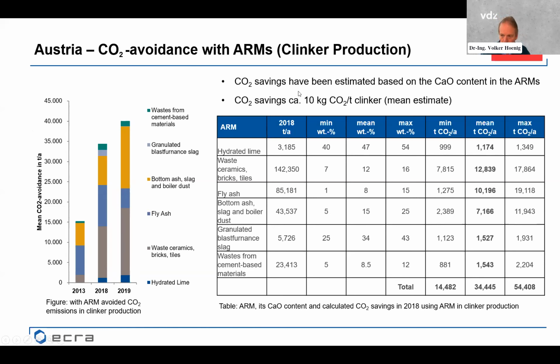So we did this based on the calcium oxide content, the decarbonated calcium oxide content in the materials. You can see here the different materials which we have assumed are decarbonated because they come already from a high temperature process. Then we have done some estimates on the composition, and going just to the mean estimate, we have come up to about 35,000 tons of CO2 per year which have been avoided by the use of these materials. This corresponds to about 10 kilograms of CO2 per ton of clinker, having in mind that producing clinker makes up about 800 or 850 kilograms of CO2 per ton of clinker.